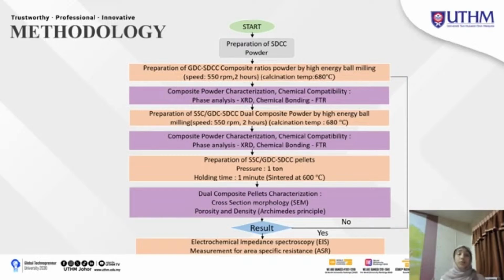So here we will be using specifically a speed of 550 rpm, for at least 2 hours, and then a calcination temperature of 680 degrees Celsius to be specific. And then next we have the composite powder characterizations, chemical compatibility, that uses the phase analysis of XRD, like I said before, X-ray diffractometers, and also chemical bonding, FTIR.